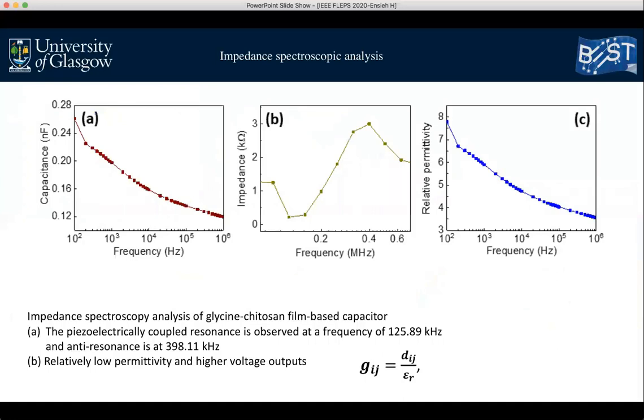And then the piezoelectric nature of the film is further confirmed from the impedance plot. Here shows the change of the capacitance with frequency. As we expected, the capacitance decreases with increasing frequency. And at the high frequency range, we observe the resonance and anti-resonance peaks at frequencies of about 130 kilohertz and 400 kilohertz, confirming the piezoelectric nature of the film.